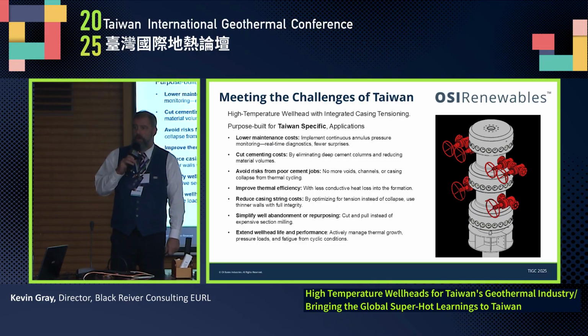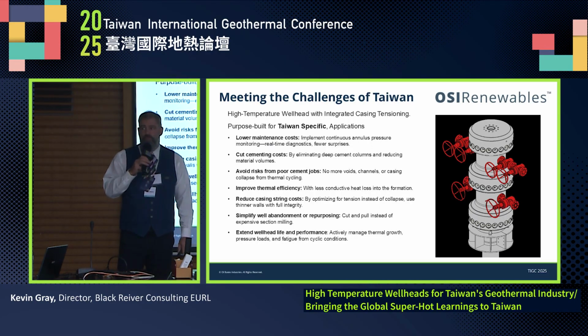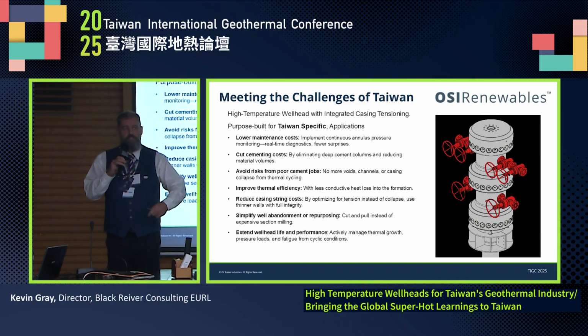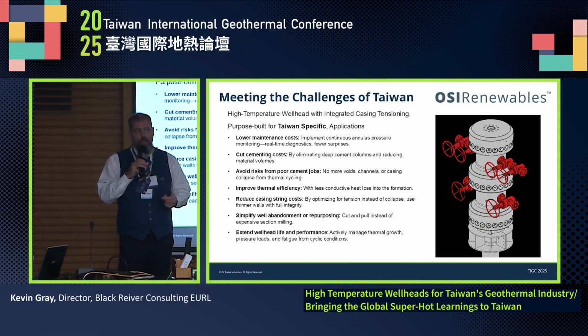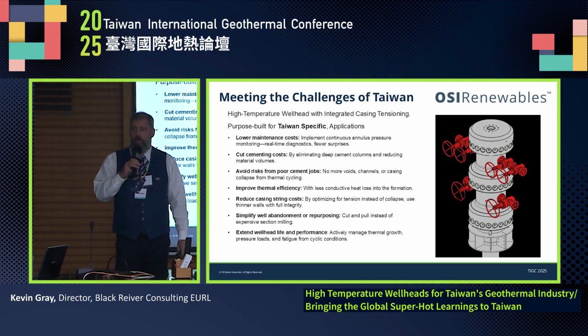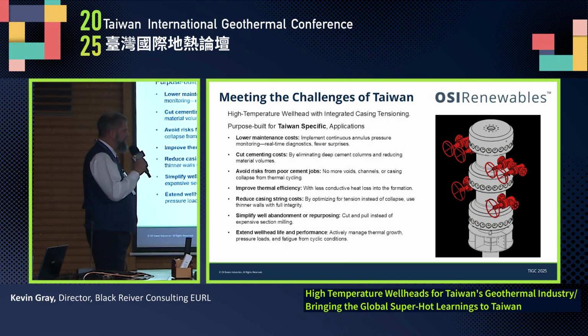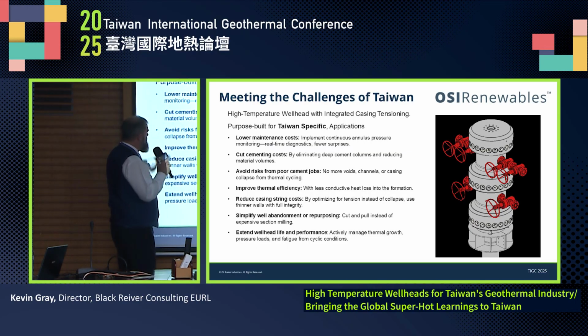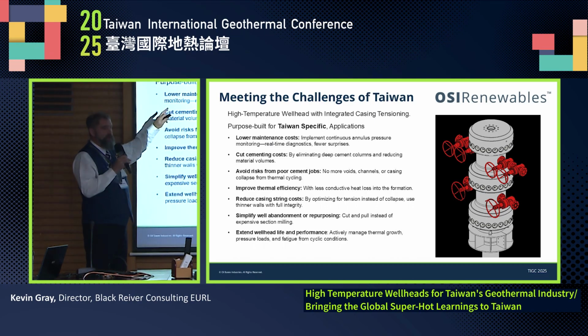as we go round the hot part of the well. If we put too much retarder in to let us get past that hot part of the well, the cement that ends up in the cold part of the well will never set. So we're potentially compromising our cement job trying to get a full annulus filled. So we can cut our cementing costs, we can make a more robust cement job.